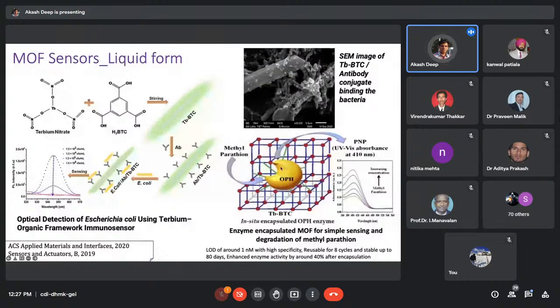When this whole compound comes in contact with the pesticides, it leads to the formation of another compound, PNP, paranitrophenol. And this paranitrophenol has a specific UV visible absorbance peak at 410 nanometer. So just by recording the UV visible spectra, once we mix these pesticides with our sensor material, we can detect what is the concentration of this pesticide in the sample.